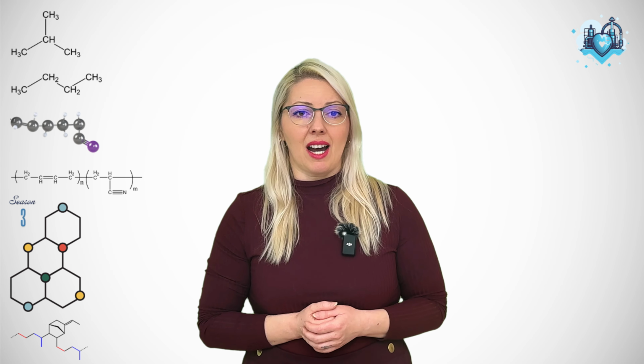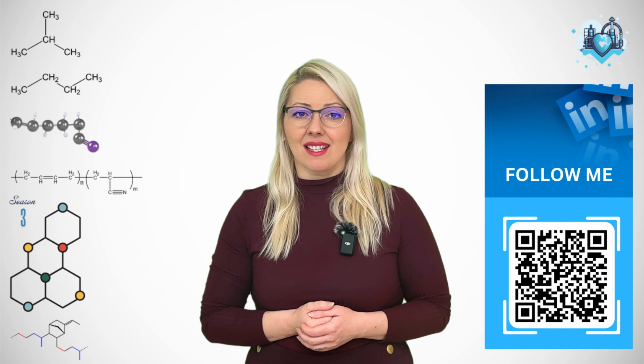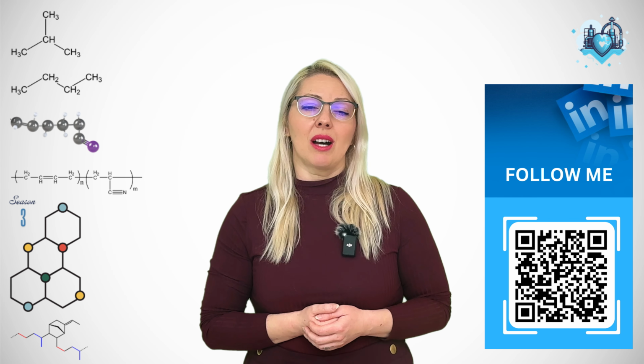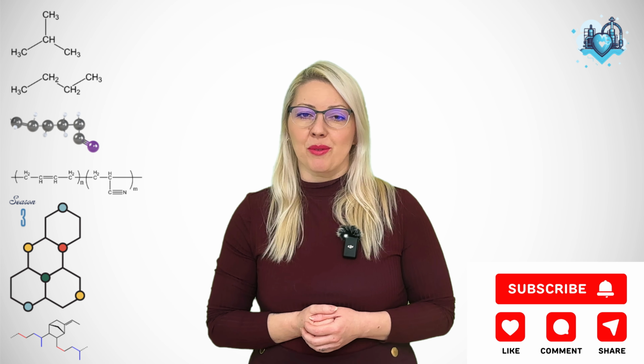The practical takeaway is simple. Oil migration is not about good or bad oils. It's about matching oil polarity to polymer polarity, oil size to network tightness, oil level to filler surface and crosslink density, and remembering that cure and service conditions lock in the final behavior. Once you understand both the why and the how of oil migration, sweating compounds stop being mysterious accidents and start looking like predictable outcomes of chemistry and structure, doing exactly what they are supposed to do.